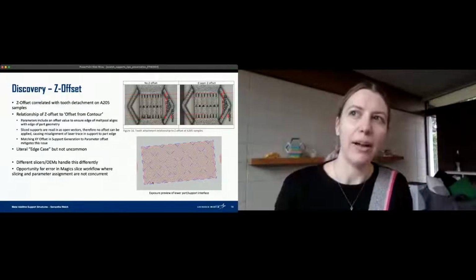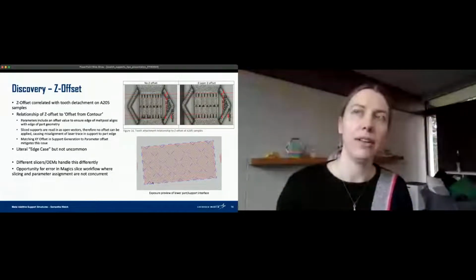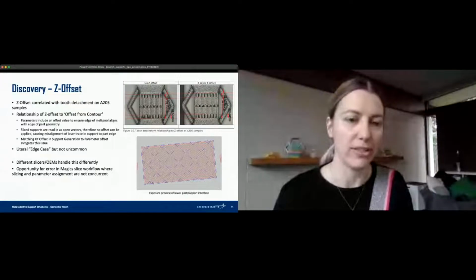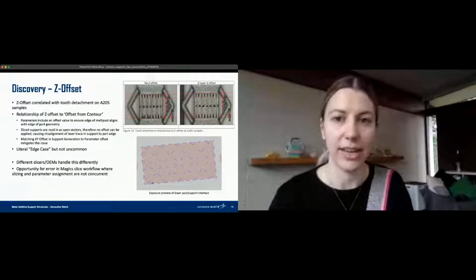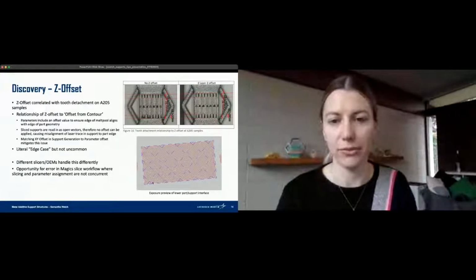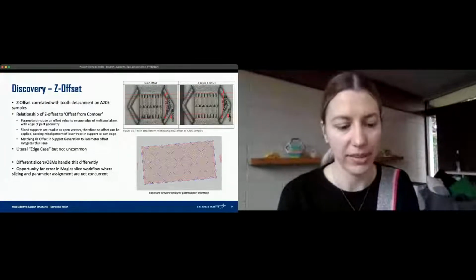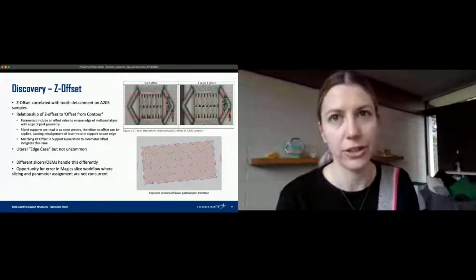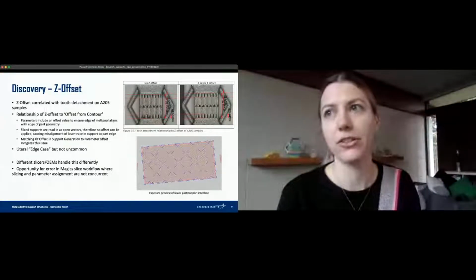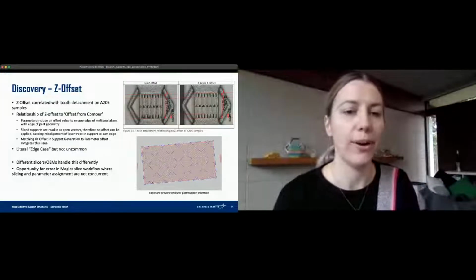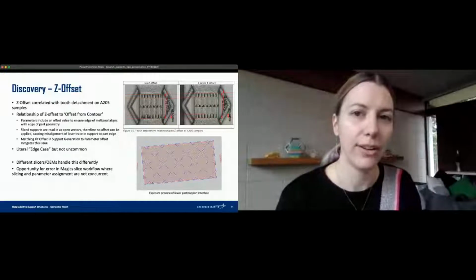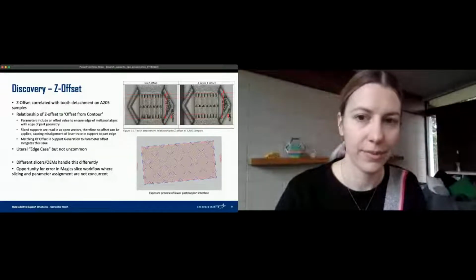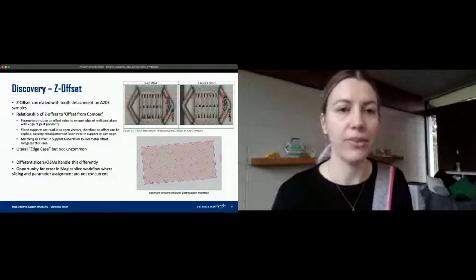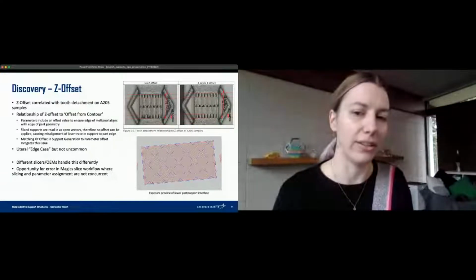It's just a very odd processing sequence because it's handled in separate software at separate points in the prep process. So it's an edge case, but if it's one that applies to your process, definitely take a look to see if this could be the root cause of some of your support failures. This was something that we observed in the Magics to Concept Laser workflow, the Magics to SLM workflow. However, if you're working with 3DXpert and EOS, they handle these more concurrently, so less of a risk there. But this is what's happening with Z offset on a single layer, at the 2D level.